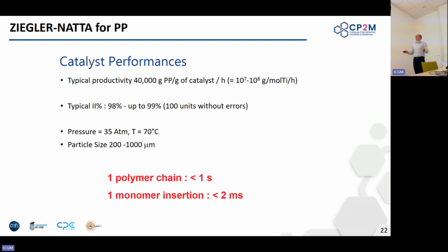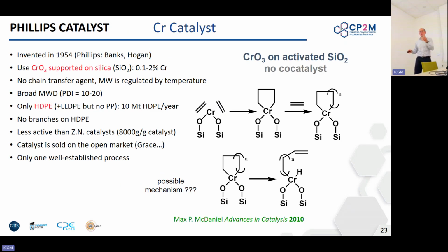The pressure can reach 35 bars, but mostly it's going to be at lower pressures, okay, slightly lower than that. And the particle size ranges from a couple of 100 microns to millimeters sometimes. I just want to mention Phillips catalysts that are very popular in the US, a little bit less on the European and Asian market. Okay, so Phillips catalyst actually predates.